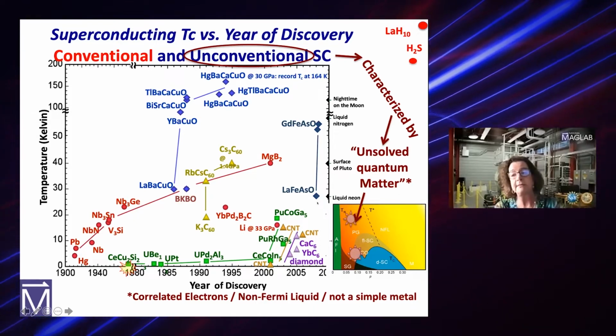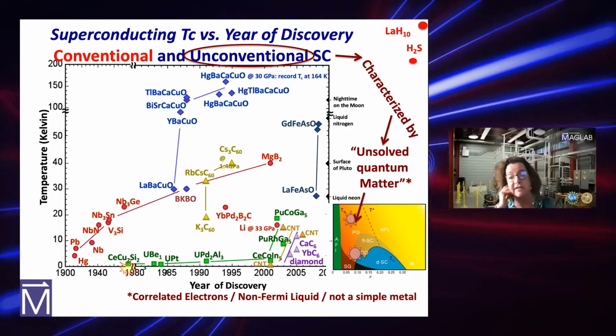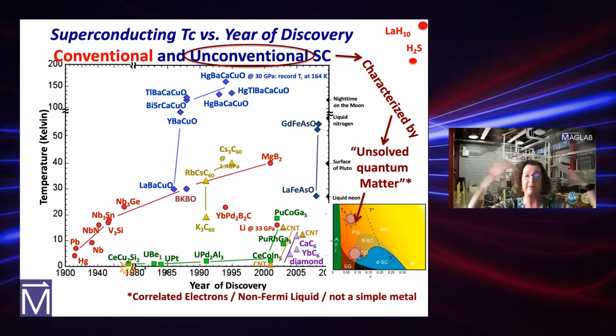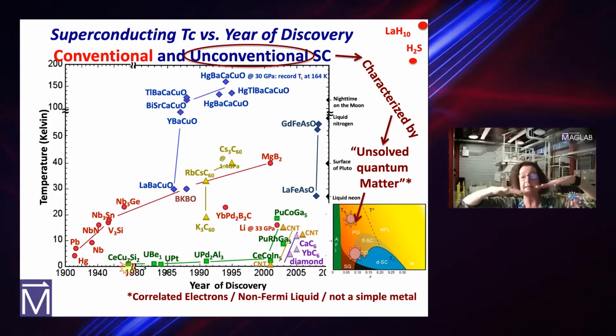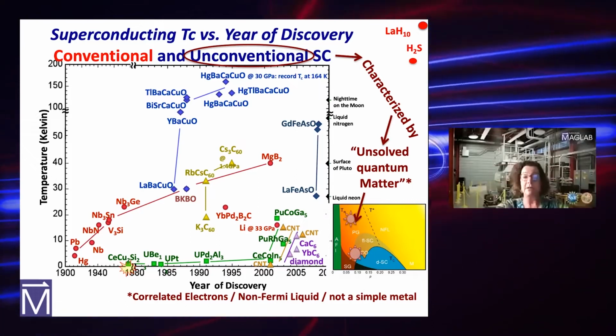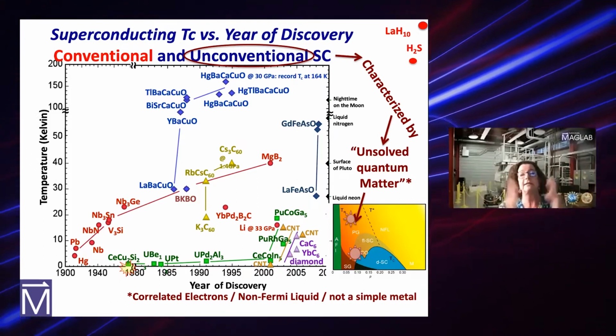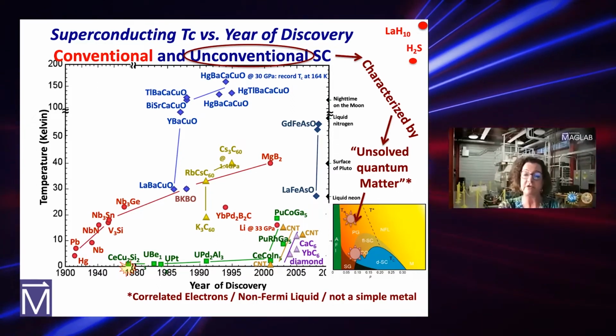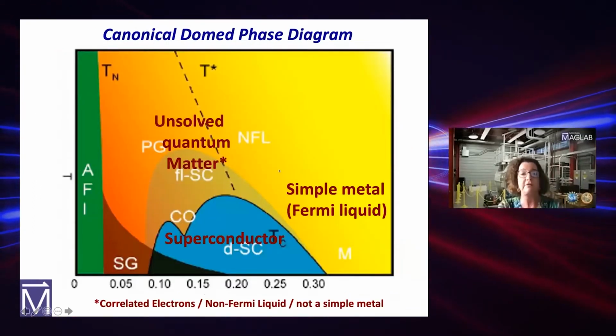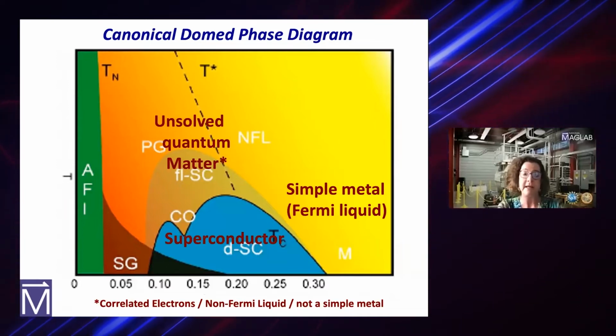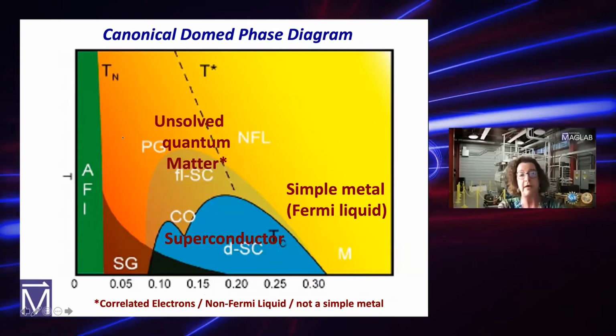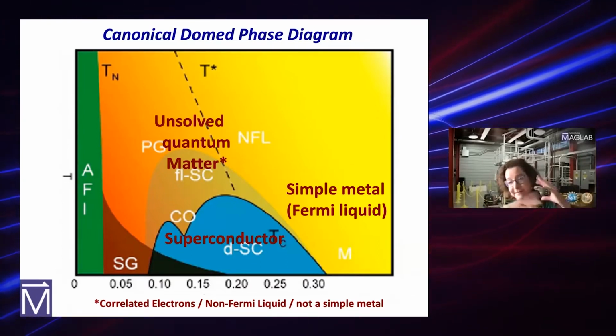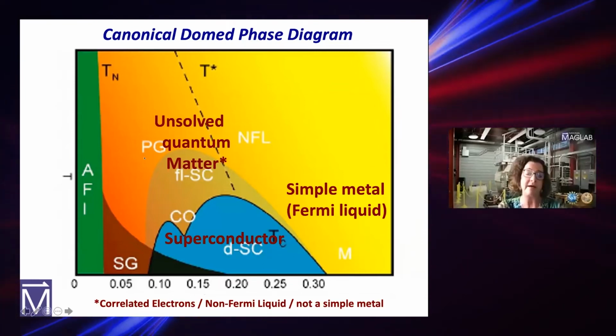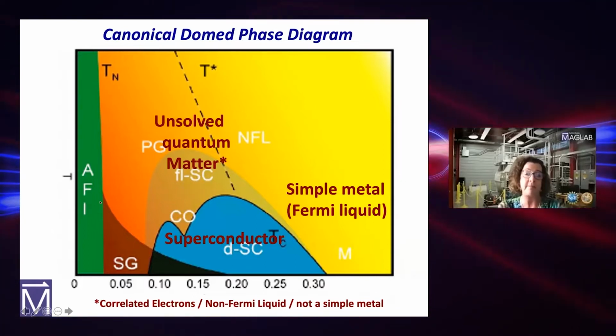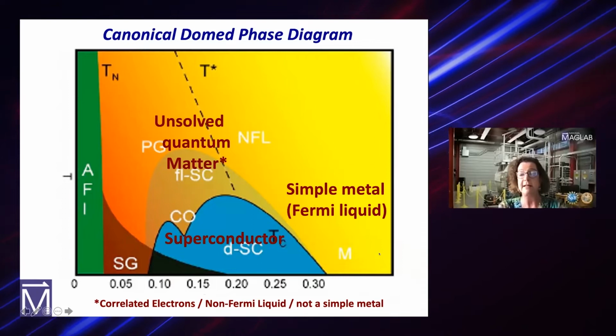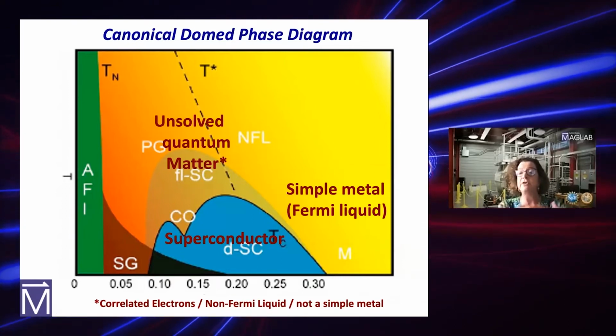Now, I define unconventional this way. In conventional superconductors like niobium, niobium-3 germanium, niobium titanium, above TC, you basically have a weakly correlated Fermi liquid, and below that temperature, you have a BCS electron-phonon coupled superconductor. I classify the unconventional superconductors as having this phase diagram. It's just a cartoon that I took. We all have our own cartoons of these things. And what's fundamentally different is that in almost all these unconventional superconductors, because nothing's everything in quantum mechanics, on one side you have typically another kind of strange metal. You can have an antiferromagnetic insulator or an antiferromagnetic metal. On the other side, which is the overdoped or the high pressure side, you can go back into a Fermi liquid.